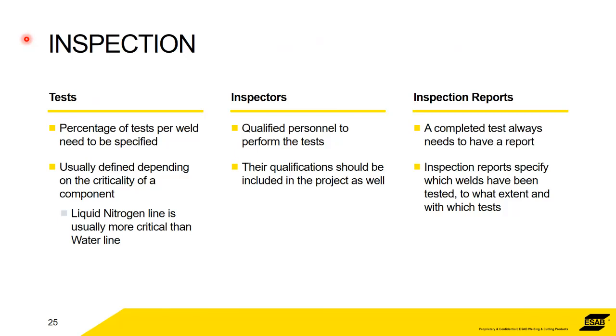than at room temperature. But in essence, all the tests need to be defined on a weld per weld basis. It could be 100% visual testing, and also 100% magnetoscopy, and then perhaps 50% radiography, which means half the welds will be tested in their whole circumference or length, or it could be 50% of every weld. So if it's a pipe, it would be half the pipe tested. That is more or less gauged based on the risk analysis of each component.